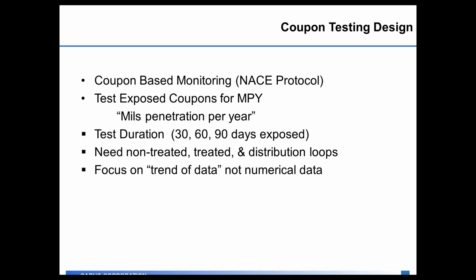What you're also going to want is a coupon rack on non-treated and then treated distribution loops. At the minimum, you'll want 2 loops, one prior to your phosphate addition and then one after your phosphate addition, to see what that treatment change is having on your coupon data. And what you want to focus on is the trend of the data. So as you make treatment changes or you change your phosphate product, is the data getting better? Are you getting better corrosion rates with your new treatment change?